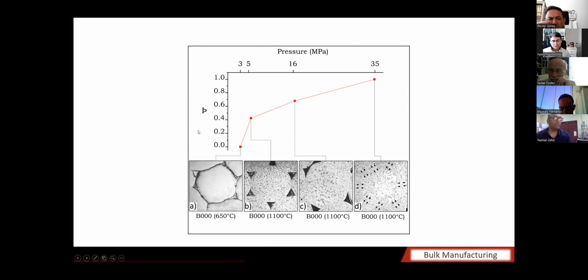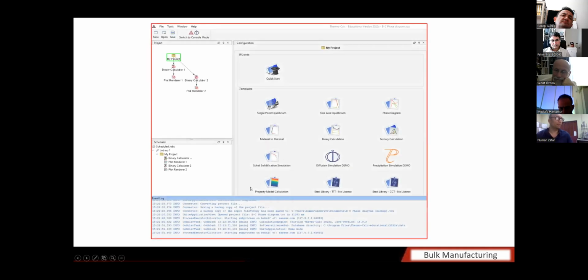It is defined by the bonded length divided by the overall circumference of the wires. And this parameter reaches 1 at this value. So we used 1100 degrees centigrade and 35 megapascal.